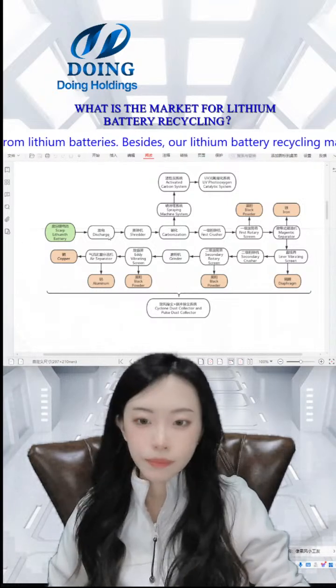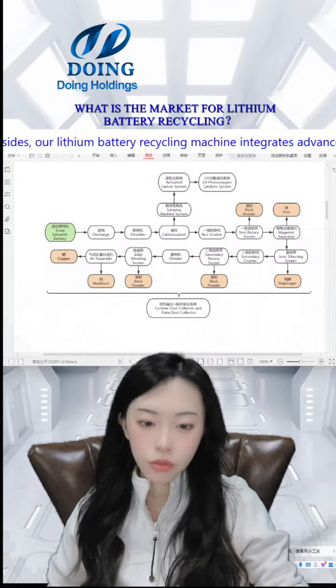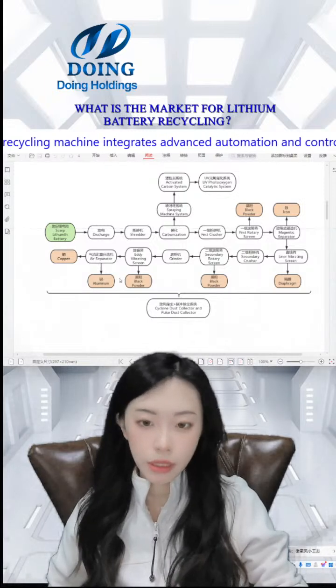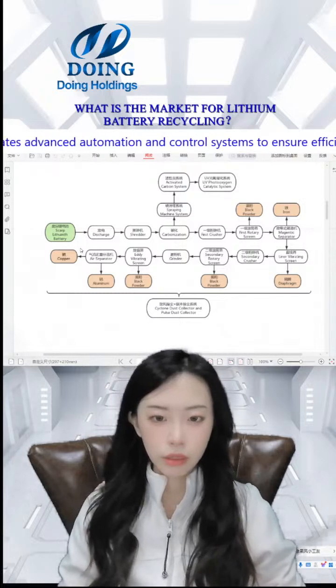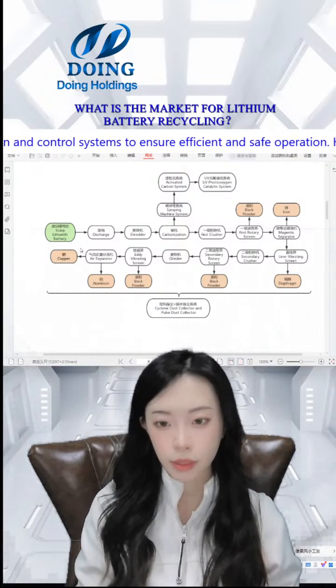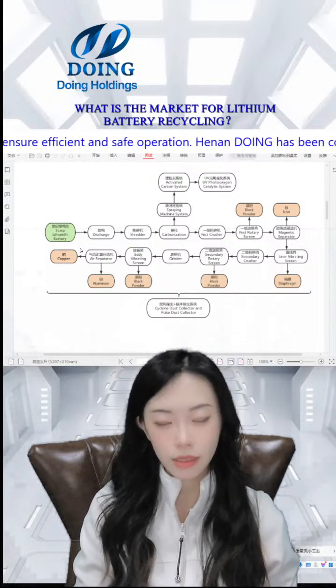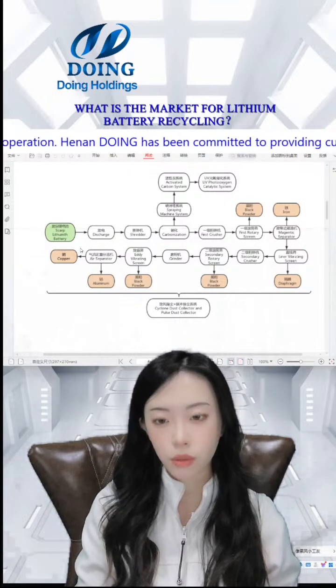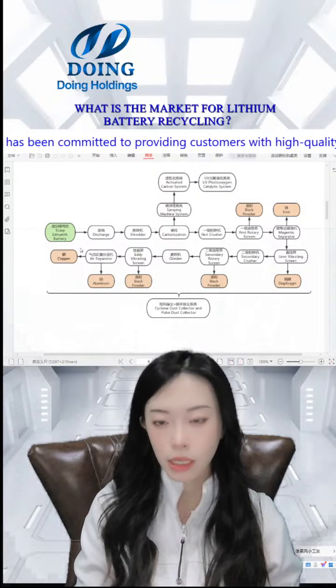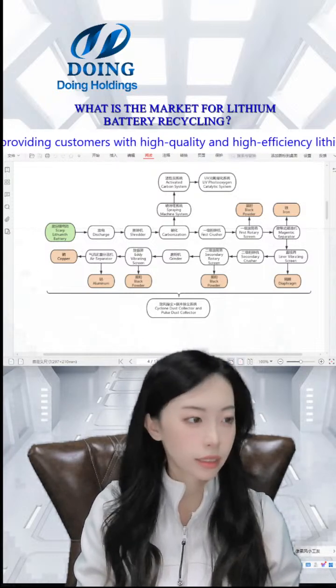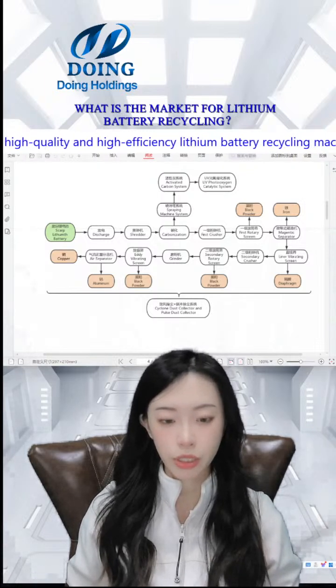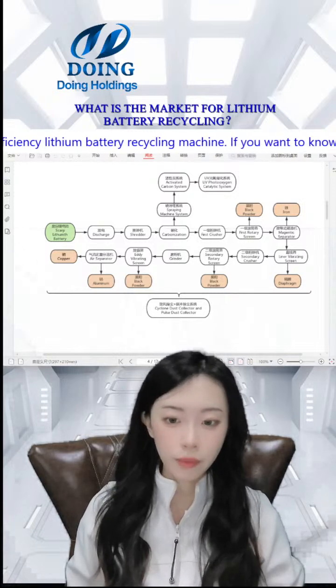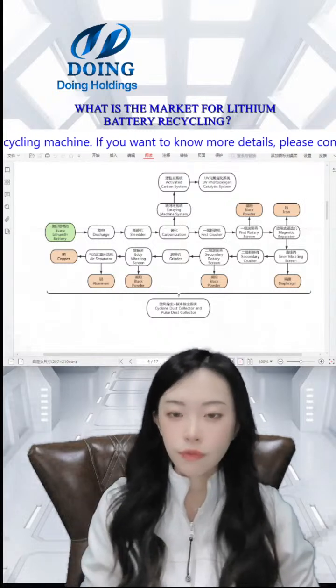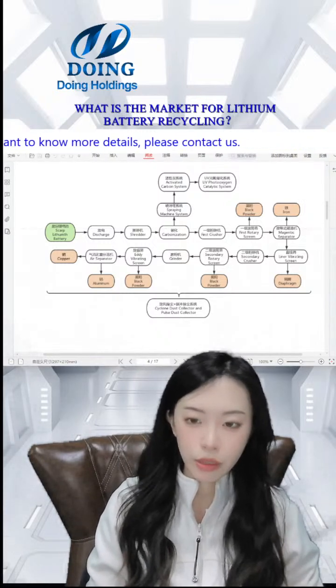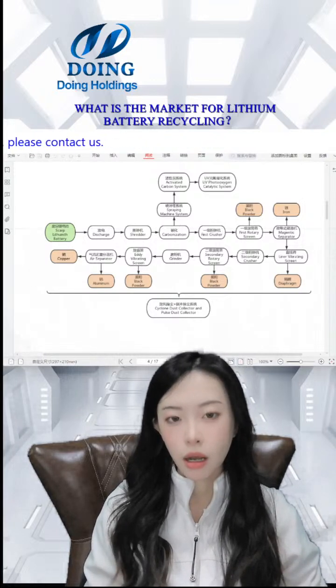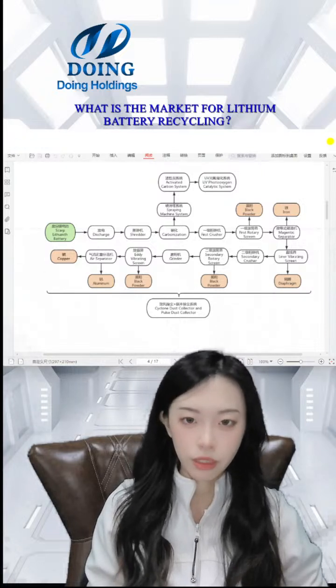Can you see the cursor? The air separation machine separates the copper and aluminium, because the gravity of the copper and aluminium is not the same. The copper is much heavier than the aluminium, so it will settle down below, and the aluminium is on the top side. This is better for us to separate, and the separation rate can reach 95% or 98%. We also have an electrostatic separator, but because the copper and aluminium are both metals, it's not very suitable for us to use this.